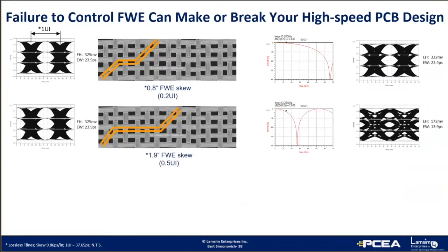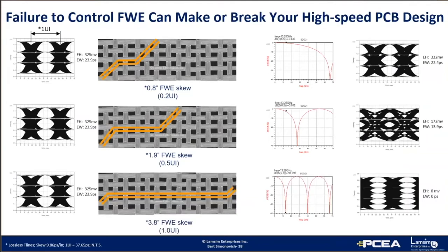But when we increase the skew to 1/2 of the UI, we observe the resonant notch moves to the baud rate and the loss increases to minus 3 dB. And the eye height reduces to 172 millivolts, and jitter increases by about 10 picoseconds. And finally, at a full 1 UI of skew, the resonant notch moves to exactly the Nyquist frequency, and the eyes are totally closed.